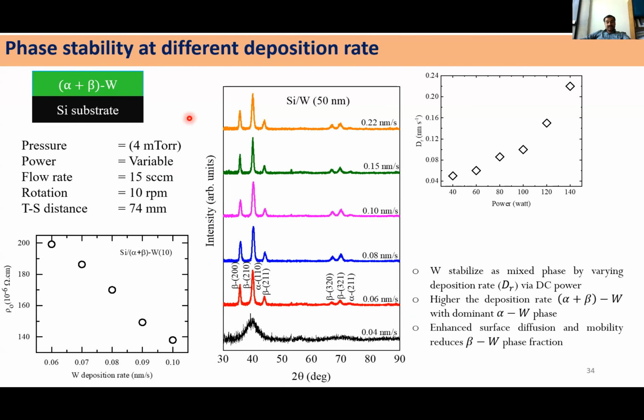And we wanted to see how it depends on the deposition rate. So at a constant pressure of 4 mTorr, when we vary the growth rate, you can see that the resistivity of this mixed phase is coming down, which tells us that when you increase the deposition rate at a constant pressure of 4 mTorr, it is possible that you can increase the phase fraction of alpha as compared to the beta. So you can make a low resistive tungsten as compared to a pure beta phase.